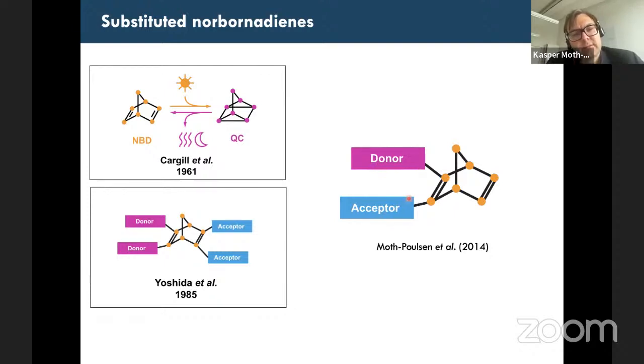It has 2 effects. One is that you have fewer donors and acceptors, so it weighs less. But the other effect is that you have a double bond here that, when we do the photo reaction, becomes a single bond. And therefore, the conjugation between the donor and acceptor is broken. And this means that the electronic communication is broken and the color is changing a lot. And that you will see later when we look at the optical properties of the system.